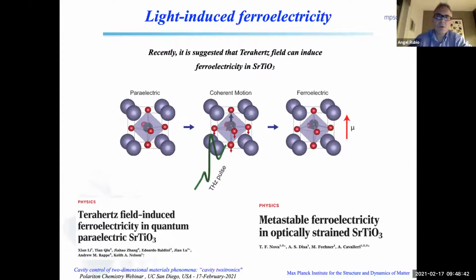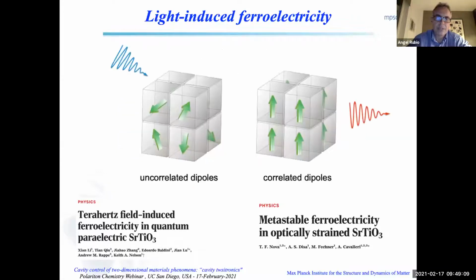If not, I give you a fast overview with strontium titanate, which is widely studied and understood. Strontium titanate in the ground state is a paraelectric material that, if you drive it with ultra strong terahertz pulses, which is exciting a phonon, you can make it ferroelectric, or transient ferroelectric. Okay, and there are different papers in which they demonstrate the ferroelectricity, at least the transient ferroelectricity, in those systems.